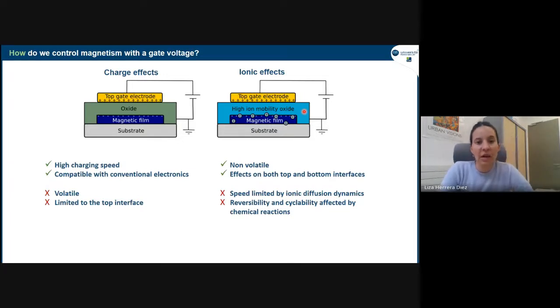On the downside, well, it's ionic, so it's slow. So that is the difference with electronics, which is the charge effects. So the speeds are limited by the ionic diffusion dynamics. And as you will see later on, most of the ionic effects are based on reduction and oxidation of the magnetic ions. So then this could create problems with reversibility and cyclability. They could be affected by these chemical reactions that take place.